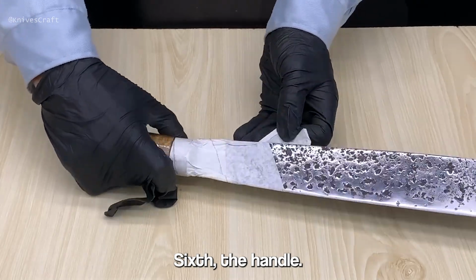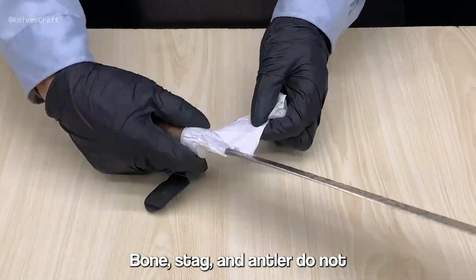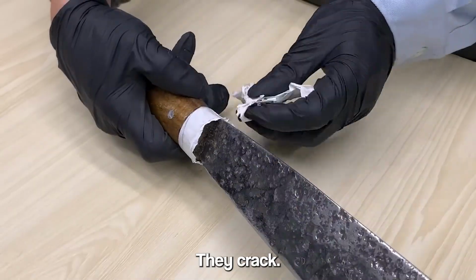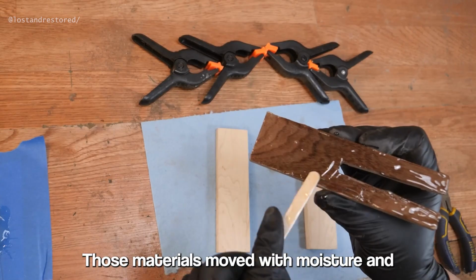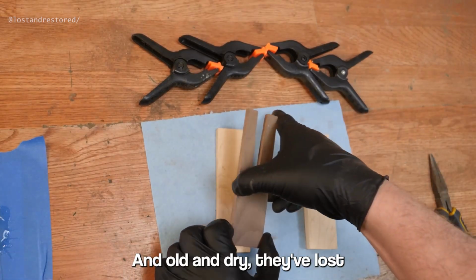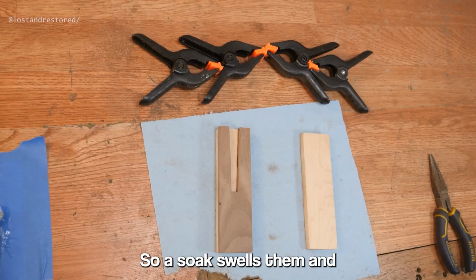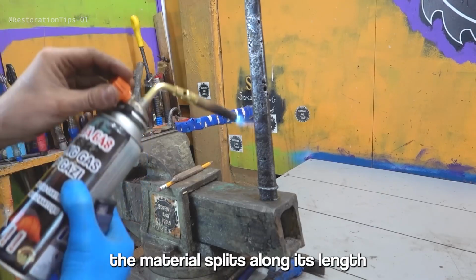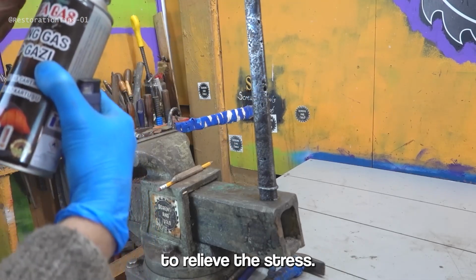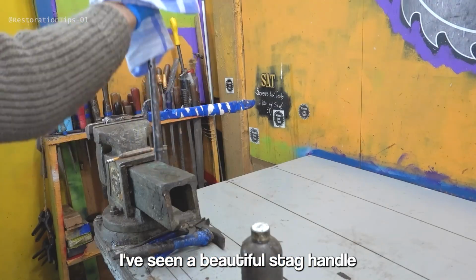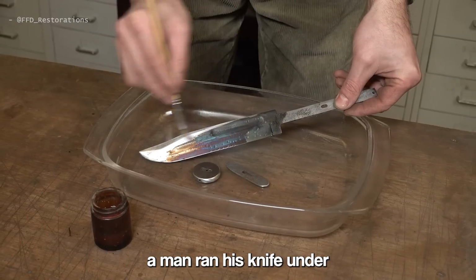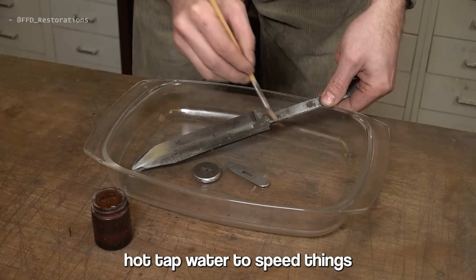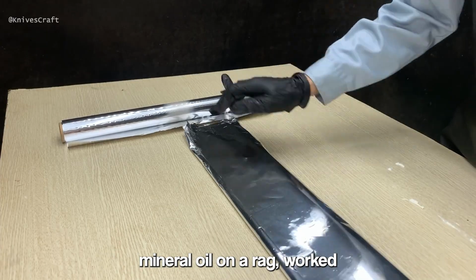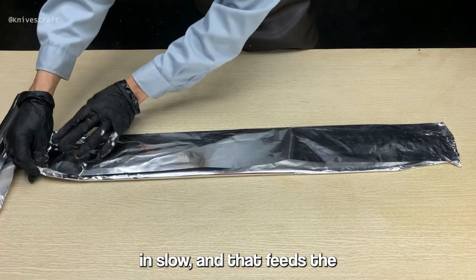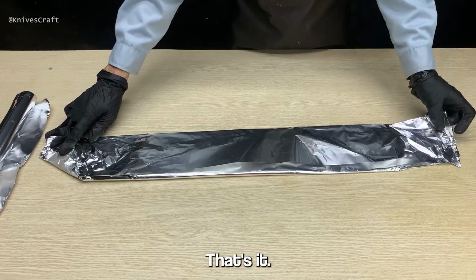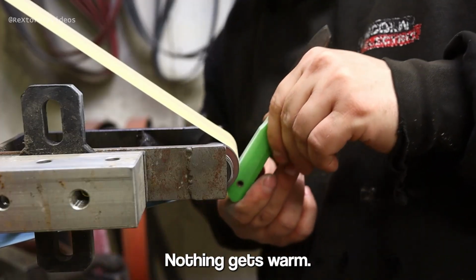Sixth, the handle. Bone, stag, and antler do not get wet and do not get warm, they crack. Those materials moved with moisture and heat when they were part of a living animal, and old and dry they've lost the give, so a soak swells them and a dry out shrinks them, and the material splits along its length to relieve the stress. I've seen a beautiful stag handle split down its whole length because a man ran his knife under hot tap water to speed things up. You clean natural handle material with mineral oil on a rag, worked in slow, and that feeds the material as it cleans. That's it. Nothing soaks, nothing gets warm.